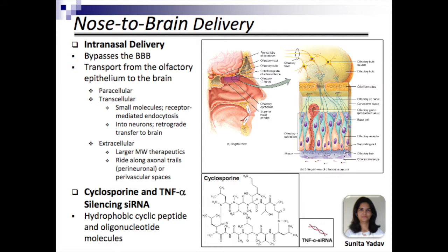of neuroinflammation. And cyclosporine is a well-known peptide. It's a hydrophobic peptide, 11 amino acids, and it's cyclized, and it doesn't require any modification because cyclosporine dissolves very well in omega-3 flaxseed or fish oil. And also in this case, we make these emulsions for delivery of these intranasal formulations by using stearylamine to enhance the residence time in the nose and subsequently allow us to get uptake and get into the brain.